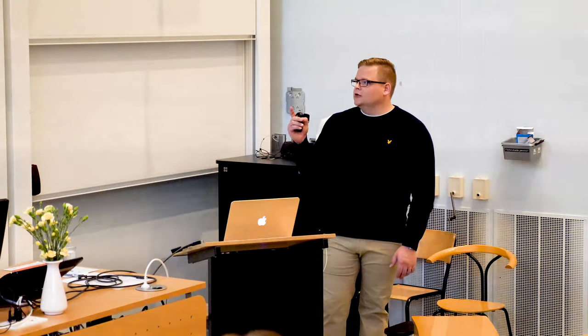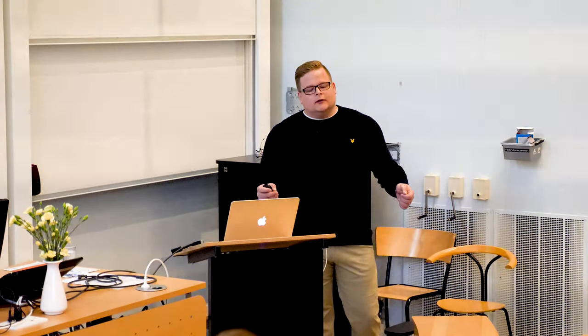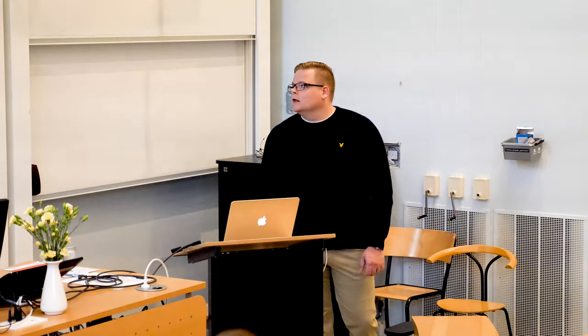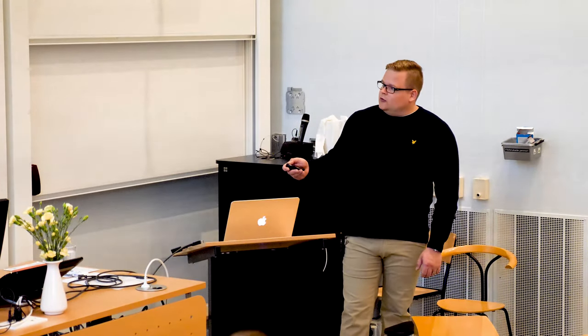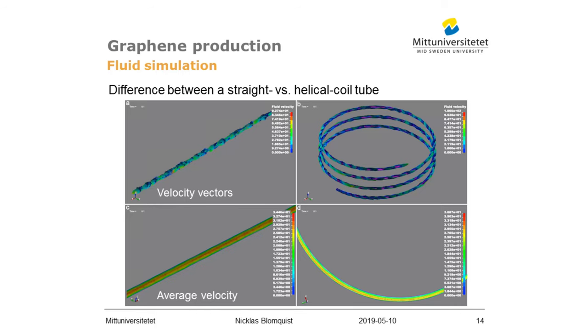To understand this, we combined simulations with experimental tests. We simulated two different geometries, a straight tube and a helical coil tube. Both of these tubes had a length of 1 meter and a diameter of 2 millimeters. The upper images here show the fluid velocity vectors in the simulation, and the two lower images show the average velocity. From the upper images, we can see that the fluid velocity vectors have more than one direction, and we have a lot of high and low speed regions. And this means that the flow is turbulent. We don't have laminar flow in the system.